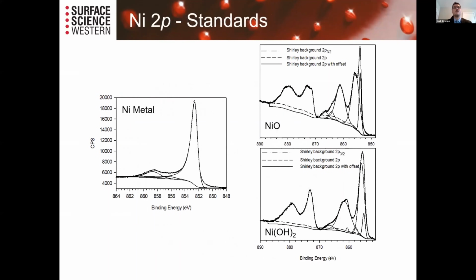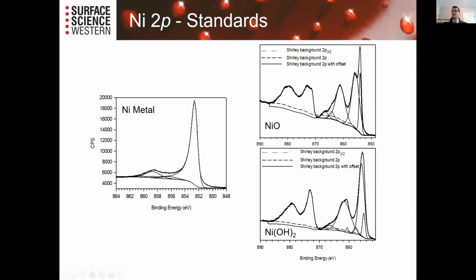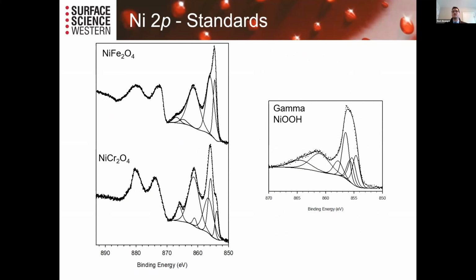For nickel, same sort of thing, where nickel metal has an asymmetric peak shape with some satellite structure. The nickel oxide and nickel 2 hydroxide have very different peak shapes. They have lots of different structure in there, so it's diagnostic of what you have. I should note that out in the literature, even now, we're still seeing cases where, instead of saying this is the whole peak shape for nickel oxide, people say this would be the nickel 2 and this is nickel 3, where really all they have is nickel 2 oxide. And again, if we look at things like the ferrite and the chromite, and then an actual nickel 3 compound, we have different structure as well for each of those.